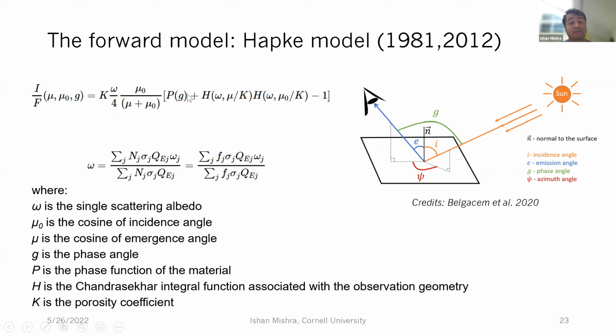Then phase function of a material is basically describing how it scatters light in terms of directional scattering. So whether it's preferentially forward scattering, backward scattering, isotropic scattering. So it just describes that. And just like for single scattering albedo, if you have different materials that have different scattering properties, then you will get a weighted average for the average phase function. H is a Chandrasekhar integral function associated with multiple scattering in the material. So it just approximates a photon getting scattered in a semi-infinite layer and how that works.